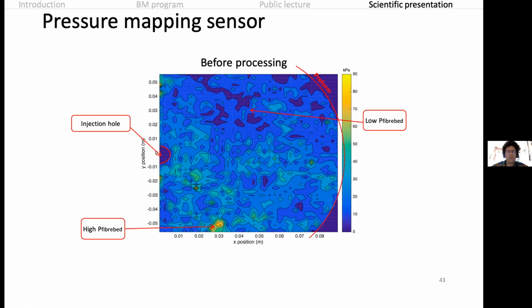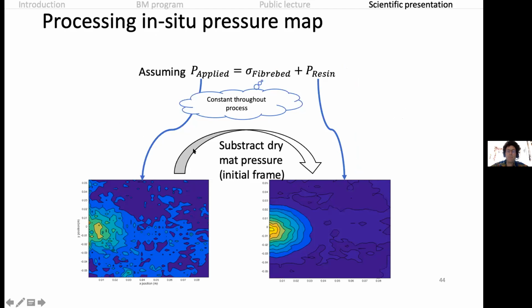This is going to influence the flow, and we can measure this pressure map while we are injecting the resin. And by doing a little bit of math and subtracting the dry mat pressure, we can obtain the resin pressure. And you see here, this is the map of resin pressure, and this actually gives a very good prediction of the flow front, which is the ellipse that we actually saw at the same time and validated with the camera and the transparent lid.